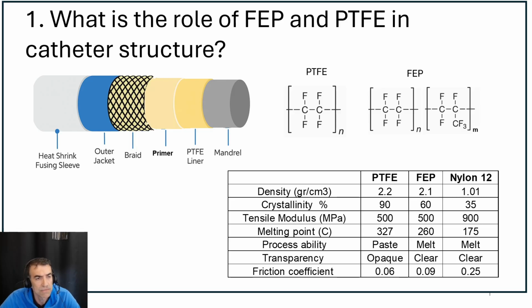But PTFE is very inert, so it doesn't stick to other materials and it will not adhere or bond with the other polymers that we have. So we first need to etch the PTFE. With etching, you are stripping some of those very stable fluorine bonds. You remove the fluorine atoms, and what happens is there are carbon radicals on the surface that are very active.